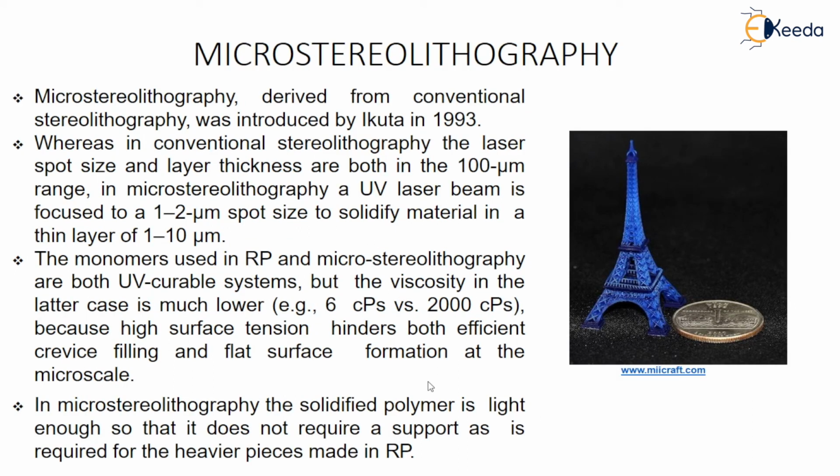Microstereolithography, that is another type of MEMS. Microstereolithography, which is derived from conventional stereolithography, was introduced by Ikuta in 1993, not 1930. Whereas in conventional stereolithography, the laser spot size and layer thickness are both in the 100 micrometer range, in microstereolithography a UV laser beam is focused to a 1 to 2 micrometer spot size to solidify material in a thin layer of 1 to 10 micrometers.